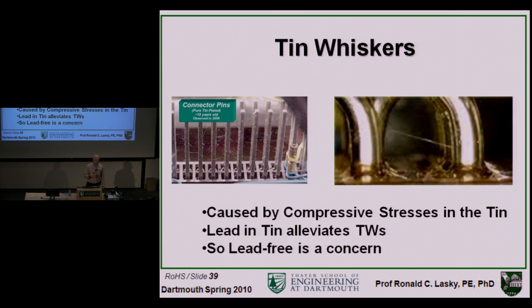Probably the most explosive issue from a reliability perspective in lead-free electronics is something called tin whiskers. It's one of these things that if you haven't experienced it before, even if you kind of understand materials, it's almost shocking. Pure tin, or a high concentration of tin, something like 90% tin or greater, if it has compressive stresses, will often produce a crystalline growth outside of the tin that looks just like a whisker and can grow literally millimeters. Here are two electrodes, and here is one tin whisker that's growing and essentially shorting to the next electrode.